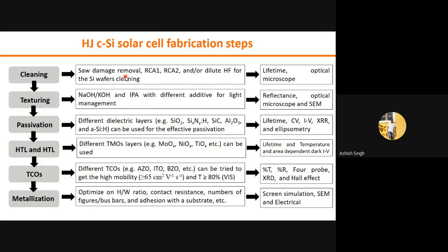And since metal wire was used in the cutting of the wafer, that kills the wafer quality, so we need to remove those impurities. The assessment of the quality of the wafer can be done from the minority carrier lifetime and optical microscope. After cleaning the wafer, we move to texturization, and a well established technique for texturization is NaOH, KOH, and IPA. The characterization should be the reflectance measurement of the textured sample. We should target to reduce the reflectance to 10% in the visible range.